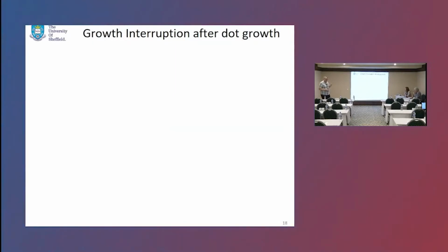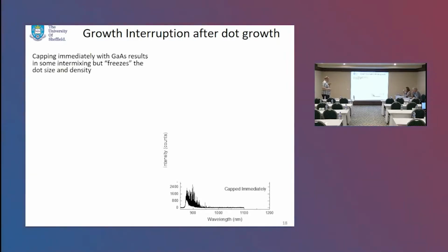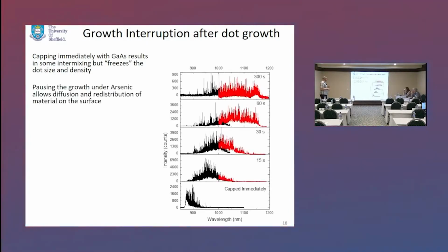So another thing we can do, one of the extra knobs that we can tune other than the ones I've already described, is just waiting. So we deposit the indium arsenide layer and then allow things to move around on the surface and see what happens. Okay, so this is now results from a planar surface. We start off with our distribution. It's quite short wavelength. It's quite hairy. Those are the individual dots. And if we then wait for a longer and longer amount of time, going up to here 300 seconds, we allow the dots to exchange material, to possibly exchange material with the substrate as well, but we end up shifting the distribution to longer wavelength. And the kind of optimal time that we're looking for to still have dots in the range that we want is kind of 15 to 30 seconds. That's what we think is kind of a good time.